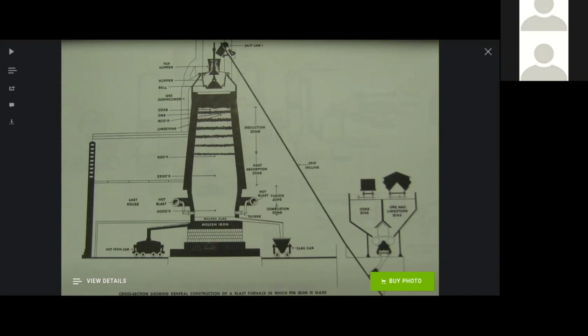So you can see the alternating layers of coke, ore, and limestone in the furnaces, and then there are also temperature markings here. It might be 400 degrees near the top of the furnace, but you're looking at 3,000 degrees by the time that hot air, which itself could be well over 1,000 degrees, comes into the furnace, and molten slag pours out. Slag is less dense than iron, so it floats on top, and it's poured out through what they call the monkey notch. And then iron at the very lowest point, and that goes into the hot metal cars. And again, we'll see more of this in detail as we move through the tour.